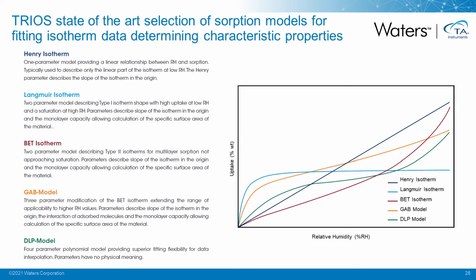If water is being adsorbed just on the surface, you can potentially understand what the monolayer capacity is in terms of weight for particular substances. With porous materials, this type of curve fitting can tell you something about specific surface area, and you can then compare specific surface areas among different materials.